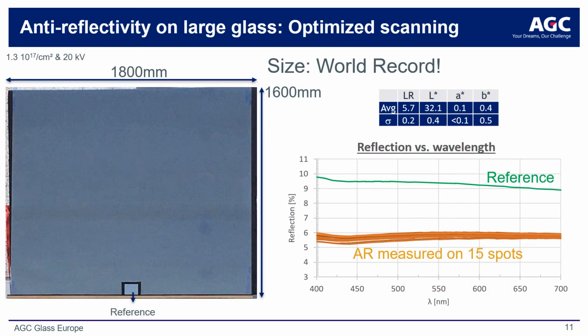Here we show the result after process optimization of a highly uniform surface treatment of a large area glass substrate. It can be seen from the reflectivity data of 15 points across the substrate surface that the reflected light percentage is stable across all 15 samples and for the entire measured wavelength spectrum. This implies a repeatable and stable surface treatment process. This is in fact the largest glass form factor ever processed with this treatment.